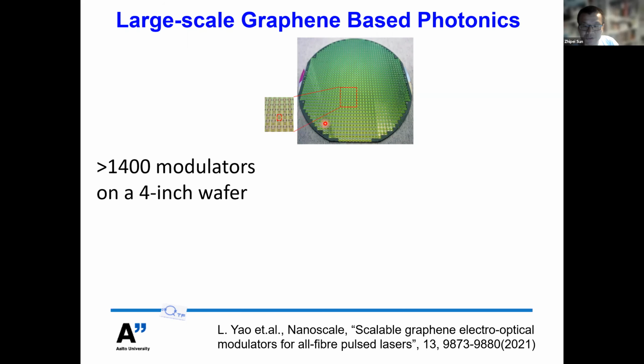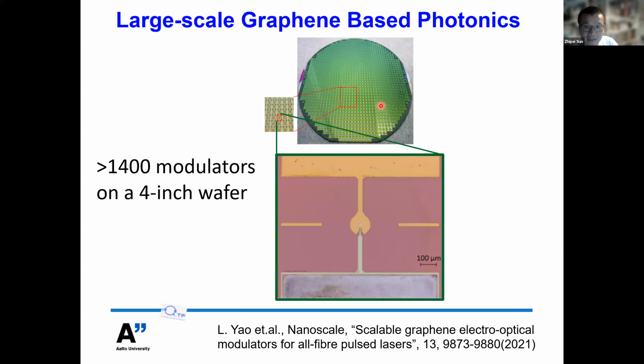This is our demonstration of graphene-based photonic devices. You can see we are able to fabricate more than 1,400 modulators on one 4-inch wafer. Here I give you a picture of how our graphene device looks. This is the bottom contact, and this is the top contact. Our graphene device is around 12 microns, which is fully compatible with optical fibers and silicon integrated devices.